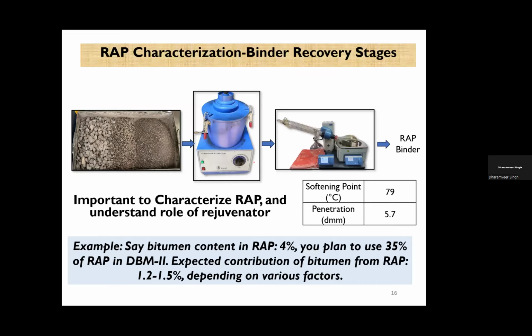For example, I'm showing the example here. If you see, the softening point of this RAP is almost 80 degrees Celsius, and the penetration is around 5.7. It looks like this particular RAP is quite stiff. Now, how much percentage do you want to use? For example, you say I want to use 30%, or you say, no, I can use maybe 50%. Then you have to be careful here.